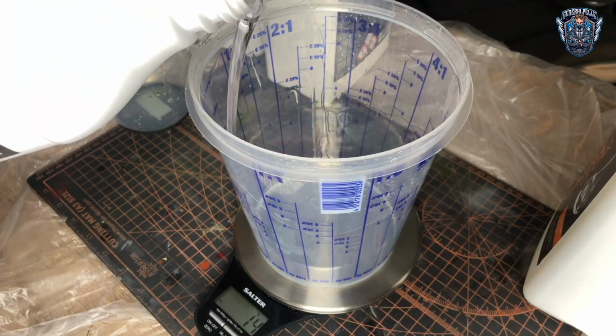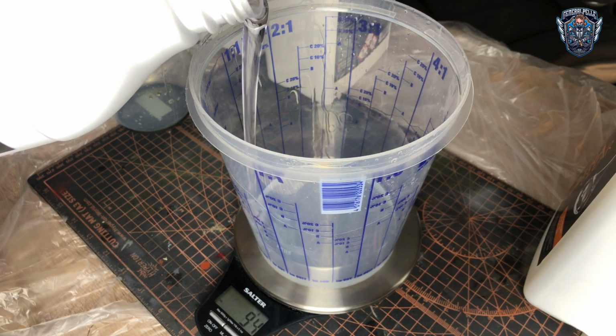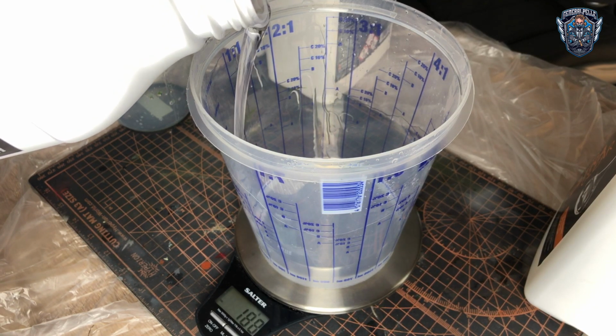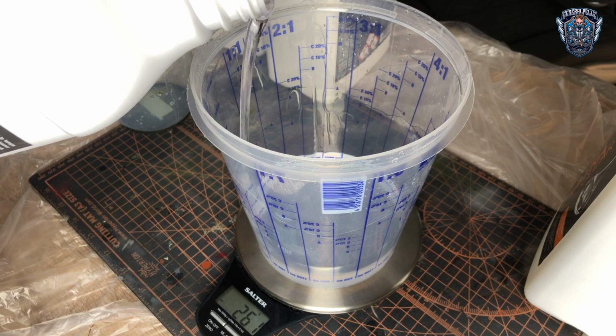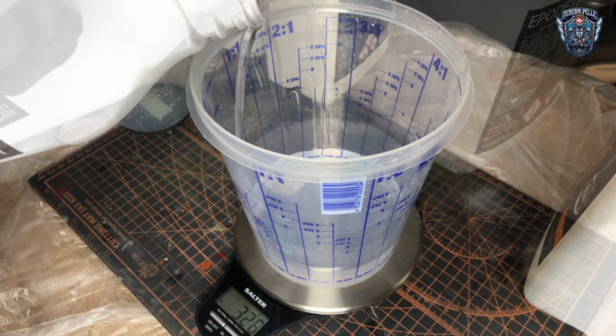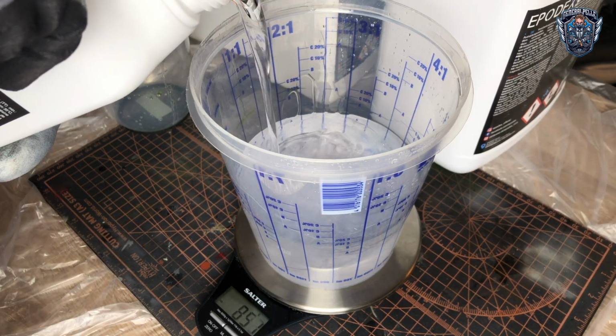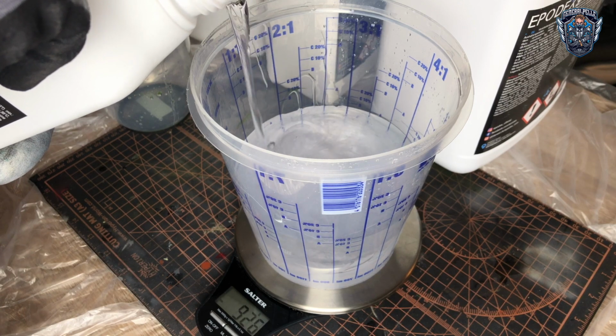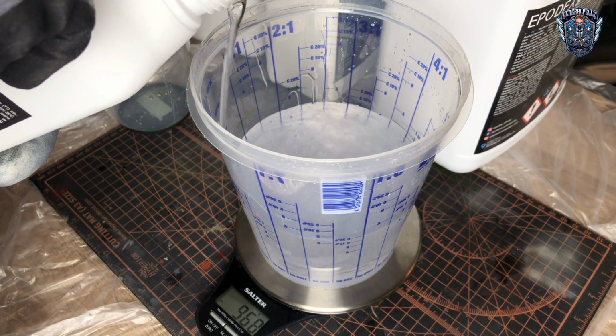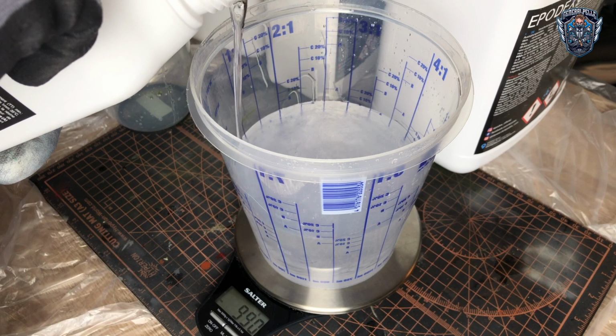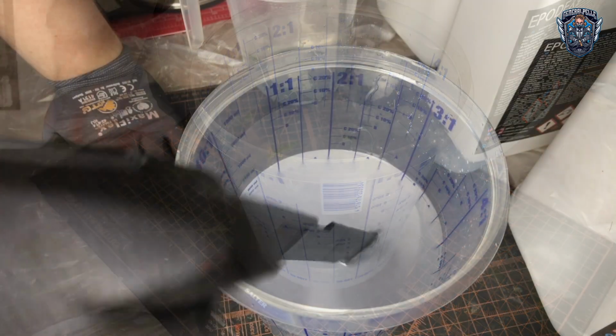Okay, off we go. This is a 2-component resin. First, the epoxy resin has to go into the mixing container and then comes the hardener. The ratio is 1:2. For each casting I prepared 1 kilogram of the liquid, which makes a total of around 6 kilograms that has been used for this diorama. Pretty crazy for someone who never used epoxy resin before, but fortunately it turned out well.